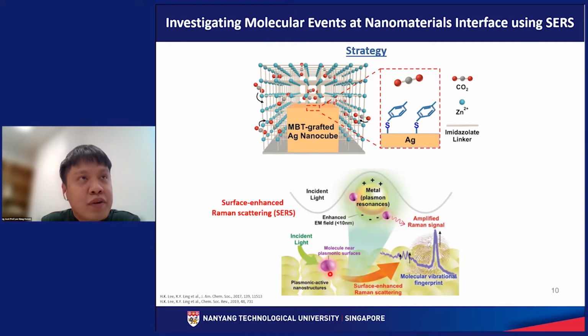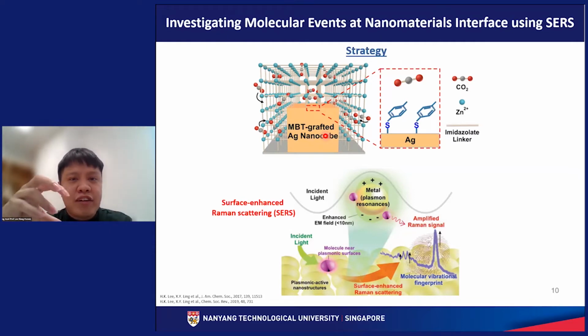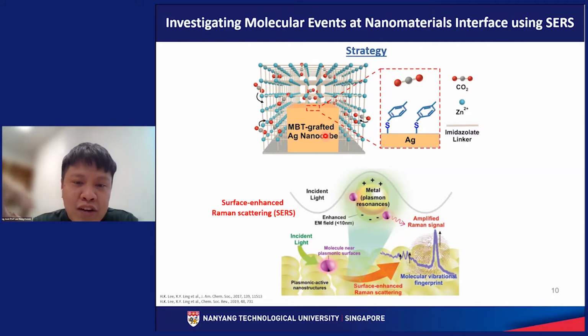secondary electric field. So this electric field can constructively interfere with oncoming light to further amplify the intensity of the electromagnetic field very close to the plasmonic active nanostructures, which in this case is our silver nanocube. Okay, so by having a very intense electromagnetic field at the particle surface, any molecules will undergo stronger Raman scattering, and this entire process will increase the Raman signal, and the process is called surface enhanced Raman scattering.